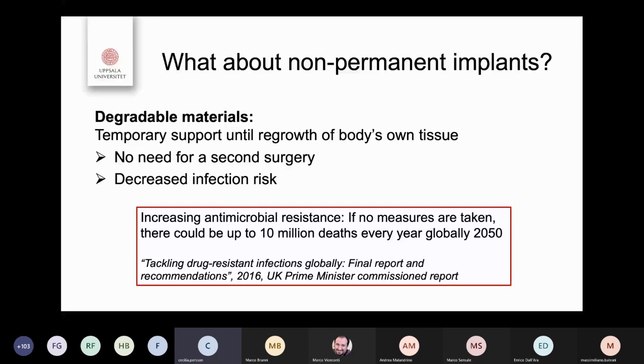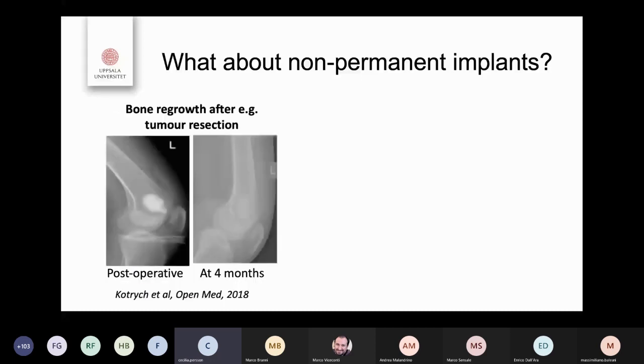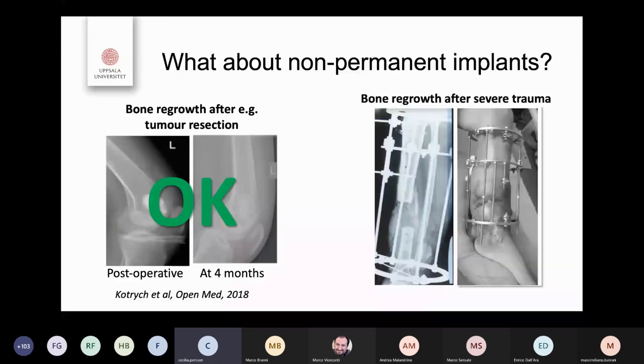And in some cases, there are solutions that work quite well. So, for example, here you can see after a tumor resection, you can fill the void with resorbable cement that is replaced by the body's own bone over time. This is an okay solution, we believe. However, when you have larger defects like this one, if you can see my pointer here, it's a lot more difficult.